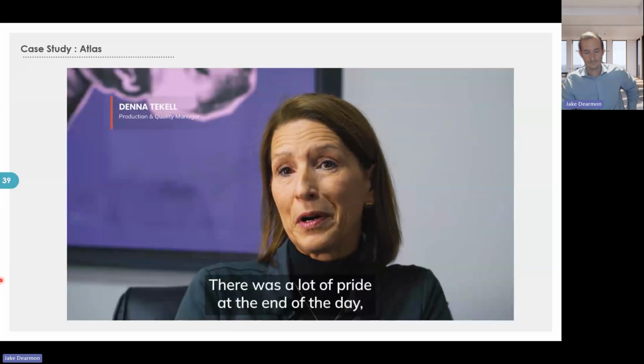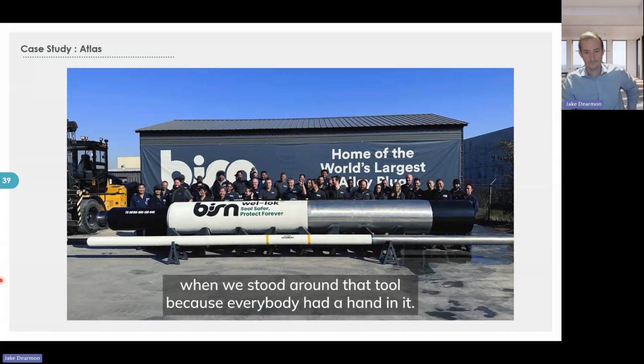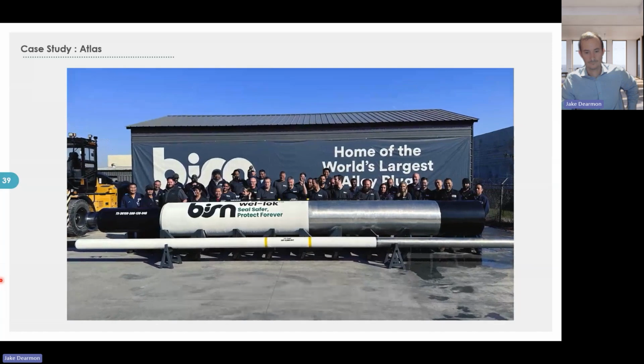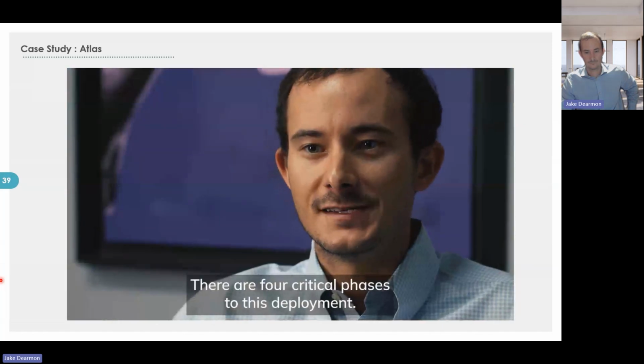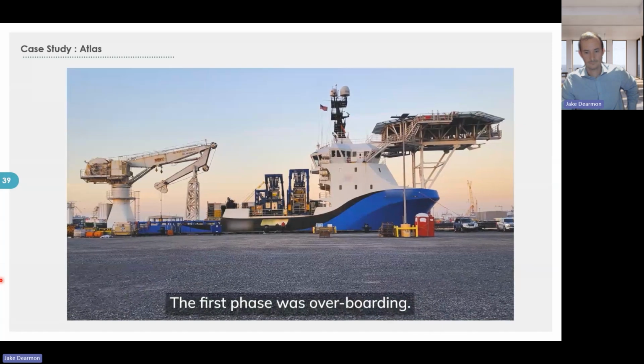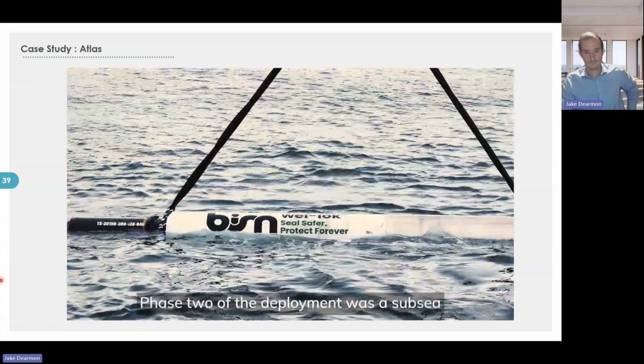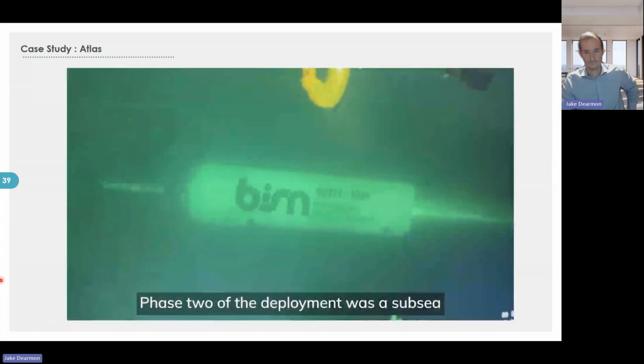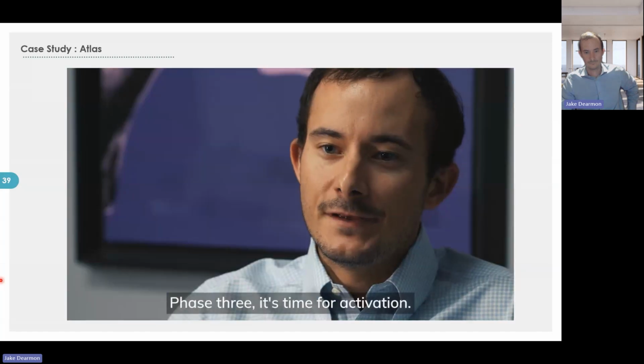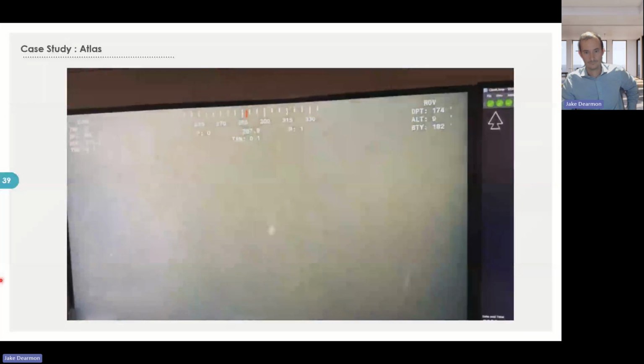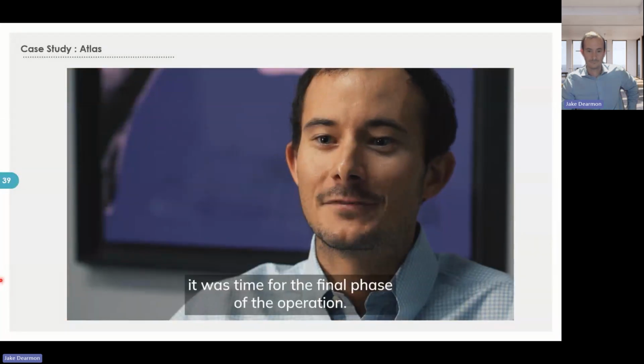There was a lot of pride at the end of the day when we stood around that tool, because everybody had a hand in it. There are 4 critical phases to this deployment. The first phase was overboarding. Phase 2 of the deployment was a subsea handover. Phase 3, it's time for activation. After a short 55-minute burn cycle, it was time for the final phase of the operation.